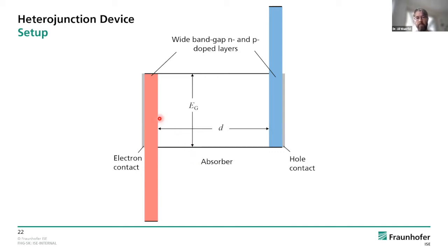And then between the absorber and the electrode itself, the contact, we insert wide band gap N and P doped layers. These represent the famous electron and hole transport layers, where there's a large variety in experiments, especially with perovskite solar cells. People try to optimize it more and more, but we already have quite a number of different materials that we can use there. For example, on the hole contact side, this blue material here could be nickel oxide, it could be PTAA. There are many different possibilities. And for the N side, it could be tin oxide, titanium oxide, or PCBM, an organic semiconductor. So there are many choices there.